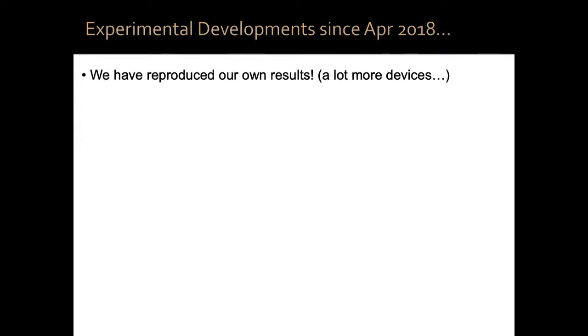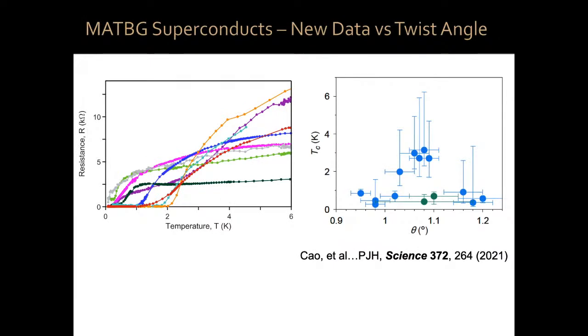Now, let me tell you more seriously some examples of experimental developments that happened since the paper was officially published in April 2018. The first thing that happened is that we have reproduced our own results. Believe it or not, that doesn't always happen, so it's good when it does. We were able to do this again, and we've done it many times. In fact, by now we are starting to produce a map of the critical temperature as a function of twist angle. That's a new knob, a new parameter in condensed matter physics, for these devices. This is actually already a bit old. We have many more data now.